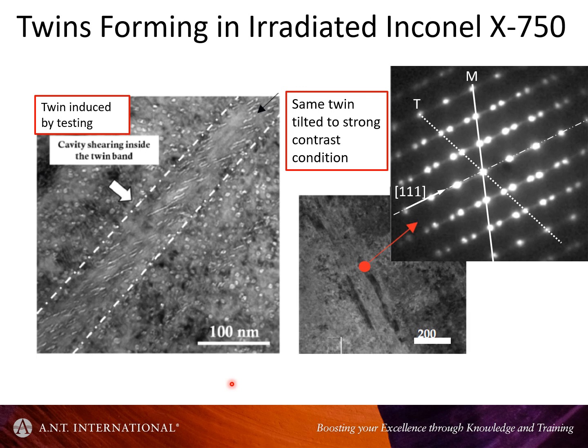A couple of points to note here. This band, we'll call this a band, is a twin. And within the twin, you can see some shearing of the implanted cavities. So these cavities would have been like this in the matrix prior to testing. Then during the testing, you induce some twinning, and this shears the cavities as shown. What's interesting is that the strain seems to be a little bit higher than the 70% strain you would get from a single twinning operation. The implication is that you could have numerous twinning operations in the same volume.